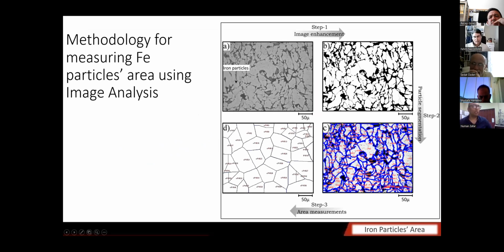So that is done using a computer program and image analysis. What you do is you convert the microscopic images into a high contrast image, and then you tell the program to draw the boundaries around each particle. And then each particle is individualized. For example, this is P20 and P24, and each particle individually is reported as a clustered image. And then using this scale, they report the micrometer square area of each particle.